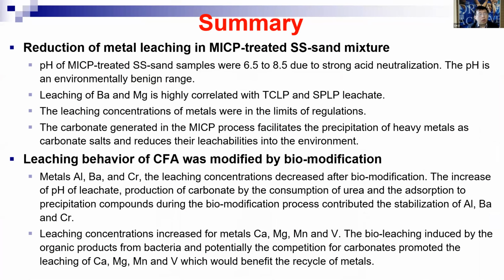So based on this work, here are some summaries. We can say that for the steel slag, if we modify it with MICP, it reduces the metal leaching. It makes less metal leach out, even though the leaching is still within the limit of regulations. Especially during MICP, the carbonates generated help the precipitation of the heavy metals. So that's reducing their leachability to the environment. So it's a benefit of using MICP to treat steel slag. I didn't present the mechanical improvements, but actually they do improve the mechanical properties, also reducing the leachability. So that's the benefit of that.